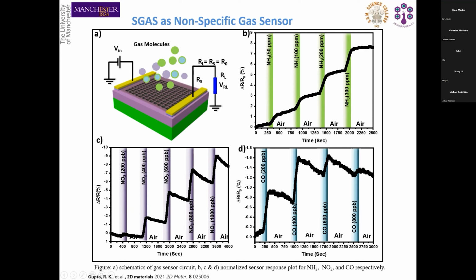So you can see a change, positive or negative, when we have interaction with ammonia or nitrogen oxide, or even with carbon monoxide. So graphene is sensitive to different gases, but it cannot identify which is which. For example, there's a negative change for carbon monoxide, as well as a negative change for nitrogen oxide. So it cannot identify which one is which, but we can easily see that there is a change when the gas interacts with the graphene.